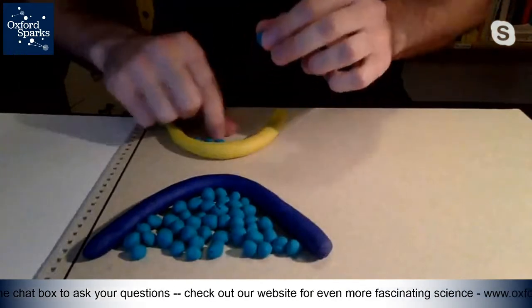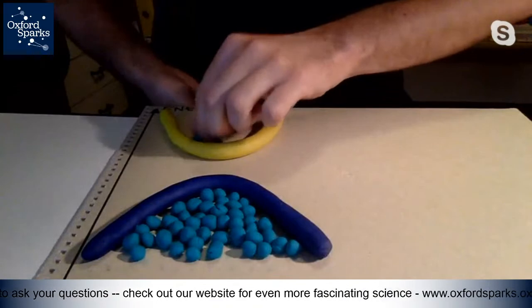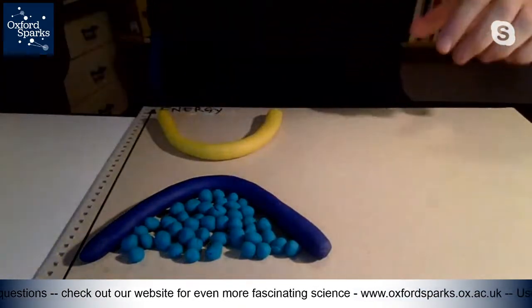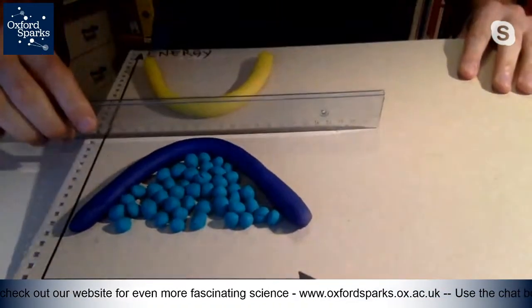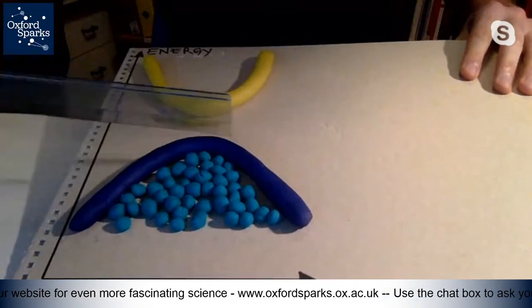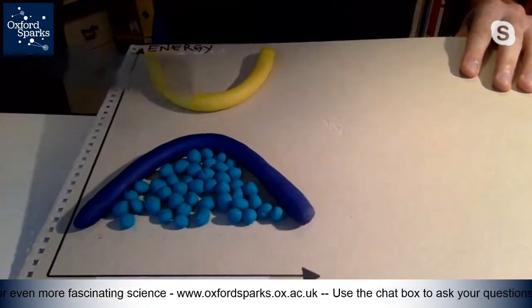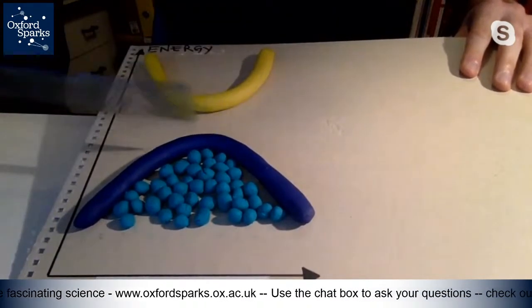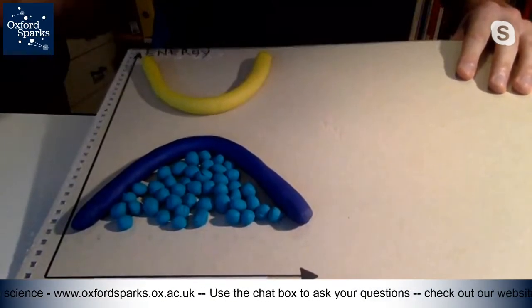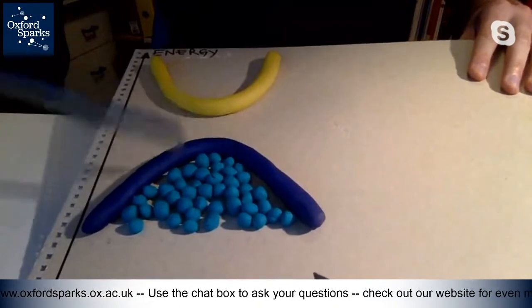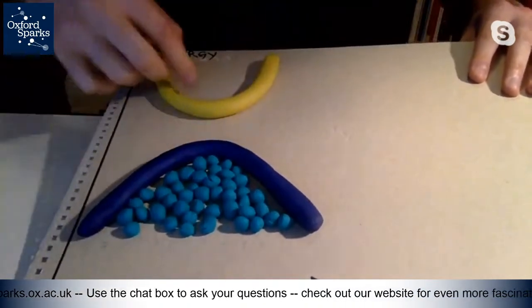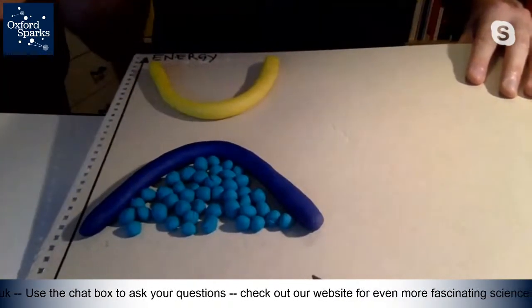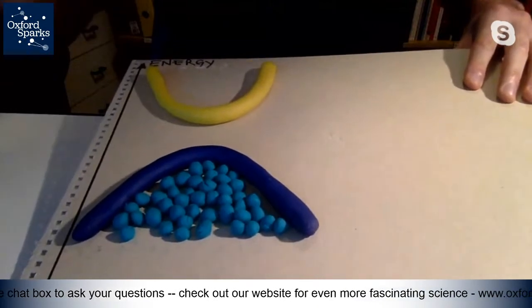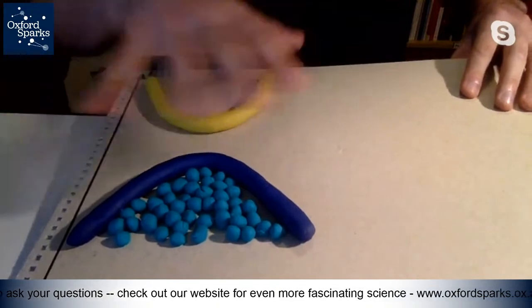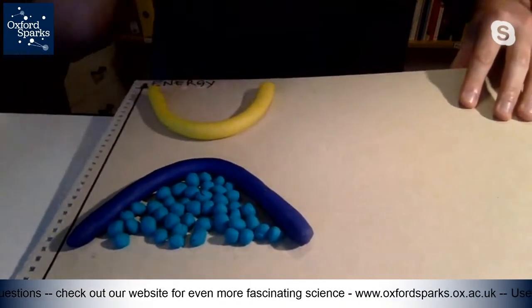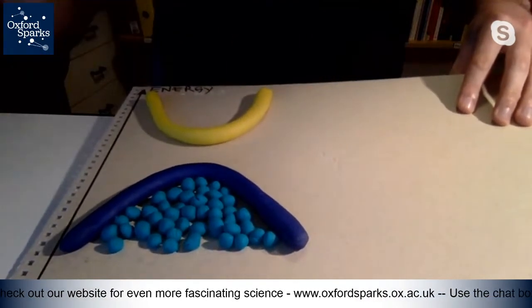But if we remove all of these electrons, and we have, oops, balls falling all over, and we have the Fermi level here, then we see that the electrons need to have a bump in energy to go from this lower band to the upper band. So that's why these materials with this type of band structure are called insulators, because there is no way that these electrons can conduct electricity because this level is already full. And they would need to hop over here, but they will require an extra boost of energy, which they do not have unless you apply some electric field, some other perturbation externally. So this is our picture of how we explain how insulators and metals work.